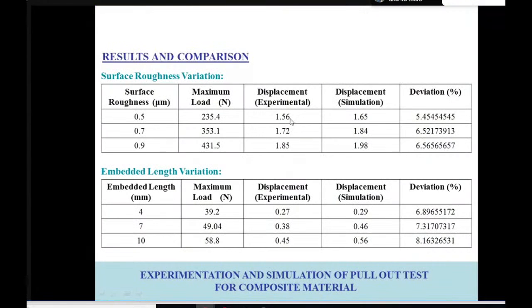So here these are the displacement results. We compare the surface roughness variation of 0.5 micrometer, 0.7. This we measured by a Mitutoyo surface roughness measurement on the rod. Then we see what is the maximum load, we can see what is the displacement, the same thing we see in the simulation also, and what is the percentage deviation we find in the result between the simulated result and the actual measurement result.